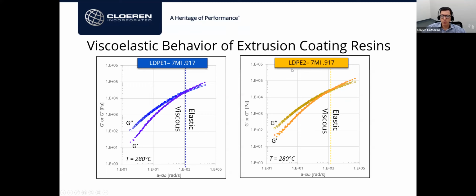And I have here another LDPE, which I call LDPE2, for a very original naming here, which is a very similar material on paper. It's also an LDPE with a melt index of 7 and a density similar to the reference material. And as you can see, the crossover point between G double prime and G prime is very similar in frequency compared to our reference material. But I can see a little bit of a difference here. My G prime seems to be closer to G double prime. So it seems like in the terminal region, the material's melt elasticity is a little higher than that of the reference material.